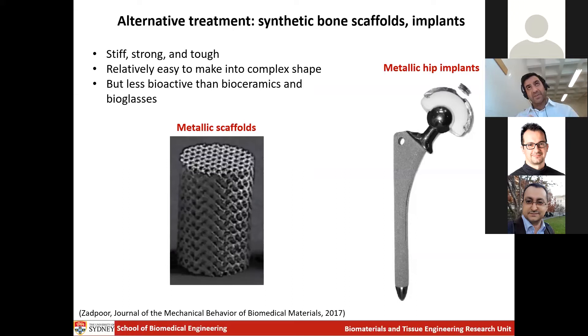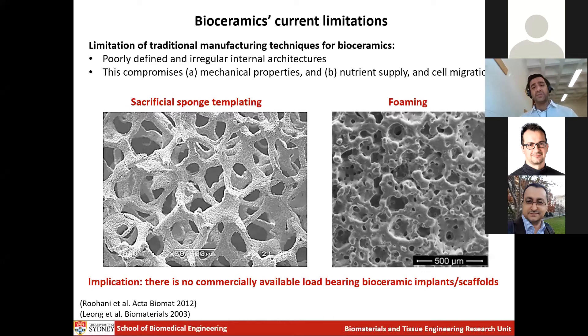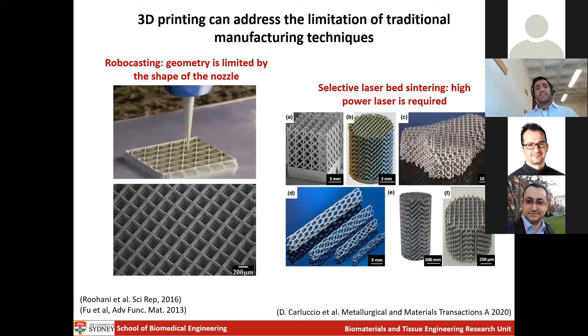In general, bioceramics and bioglasses can offer much better recapitulation of the biophysical and biochemical properties of bone than metallic implants. The problem with ceramics is twofold: it's hard to form them into complex shapes with precise internal architectures without sacrificing mechanical properties, and they are not tough. Bioceramic scaffolds developed through traditional manufacturing techniques like sacrificial sponge templating have irregular internal architectures that compromise mechanical properties due to stress concentration, and the interconnection between pores is poorly controlled, compromising nutrient supply and cell migration — limiting tissue regeneration capacity.